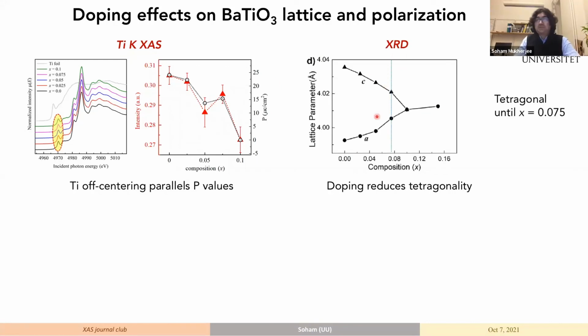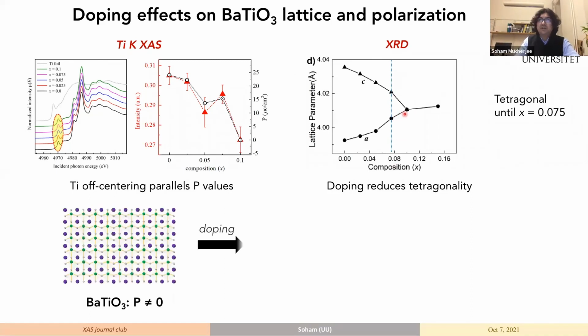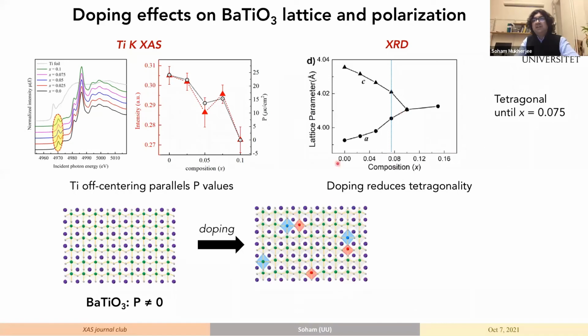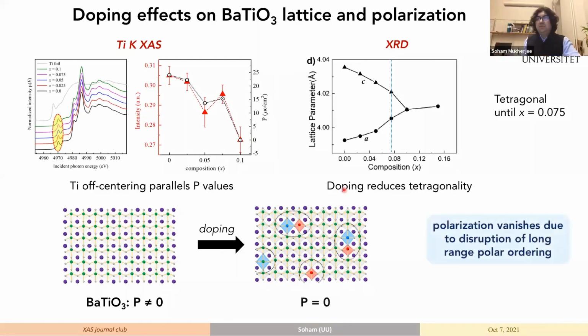And the diffraction shows exactly the same thing, that the system stays tetragonal until 7.5% doping, beyond which it becomes cubic. So what essentially happens is that when you dope, you create local modes which disrupt the polar ordering of titanium in the system in BTO. And eventually beyond 7.5, the moment you try to dope, the system loses all its ferroelectricity.